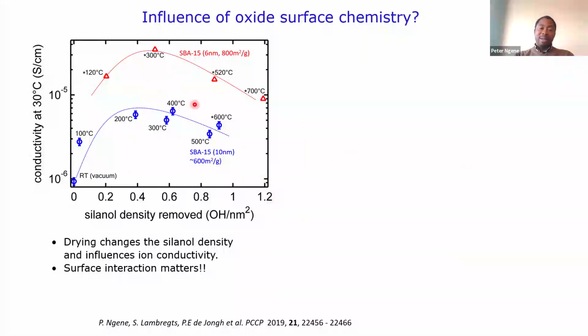So you can see already that the pore size being different gives rise to different conductivity. So what do we know? If you dry this oxide at different temperatures, we can actually change the density of the surface groups. You can see here that the density of the surface group changes by just drying at different temperatures. And this is what we did: vacuum dried, dried at 100 degrees centigrade, 200.